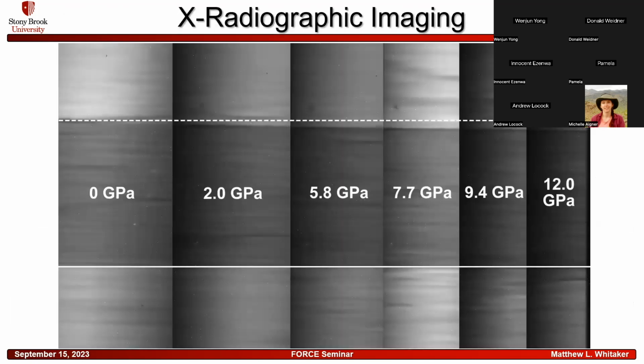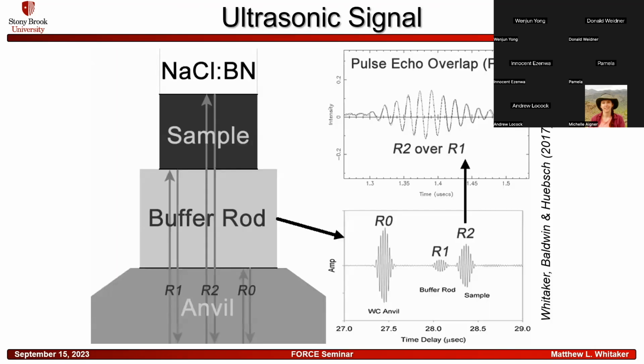So this is just an example of the X-radiographic imaging evolving as we go from 0 to 12 GPa. You can see that the sample gets consistently shorter as we go, which is exactly what you would expect to happen in the experiment. The ultrasonic signal is sent into the sample from a transducer on the back of the anvil. The signal travels through the anvil and the buffer rod and into the sample, and the reflections on those different surfaces are shown in the diagram at the lower right.